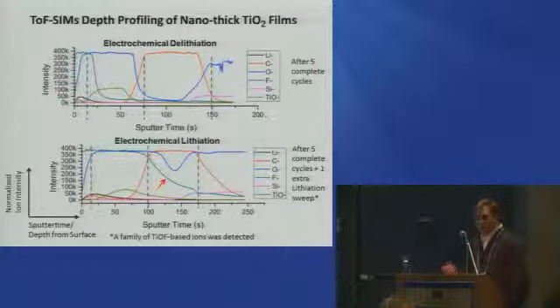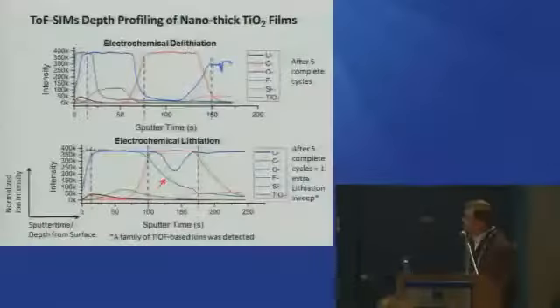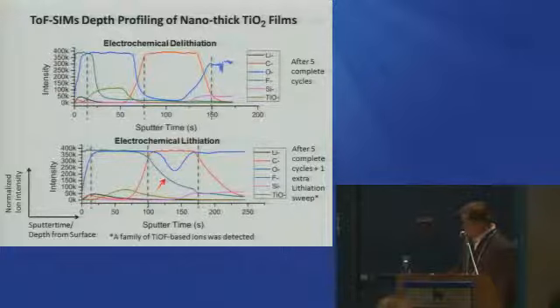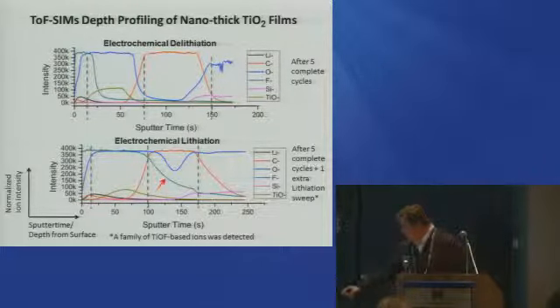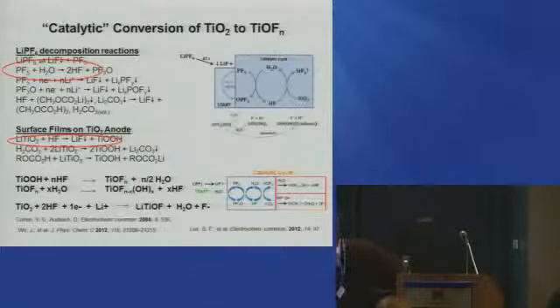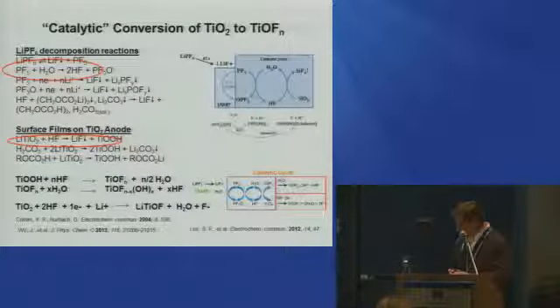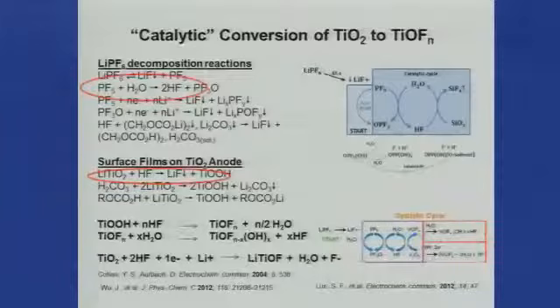So to me, this was actually really surprising. I could not understand why you get so much fluoride that goes all the way through the film. And it looks like it's reversible. So when you actually delithiate, most of the fluoride comes back out. So we thought about this in another context. And it has to do with the fact that the salt itself can decompose.